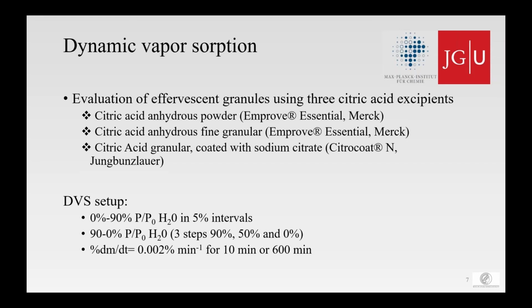Since we expected the sample to take up a lot of water, we chose a not so strict equilibrium criterion, and we also chose a long time frame of 600 minutes if the equilibrium criterion cannot be reached, so that the sample has much time to possibly reach its equilibrium.